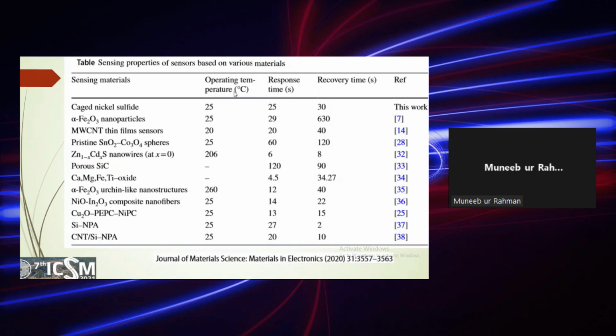The operating temperature in our case was 25 degrees C, room temperature. The response time that we noted is 25 seconds, and the recovery time was 30 seconds. For alpha Fe2O3 nanoparticles, the author in reference 7 observed that the response time of their devices was 29 seconds, and the recovery time was 630 seconds, which is quite high. In comparison to this alpha Fe2O3 material, this cage nickel sulfide material showed a very quick response and recovery time.